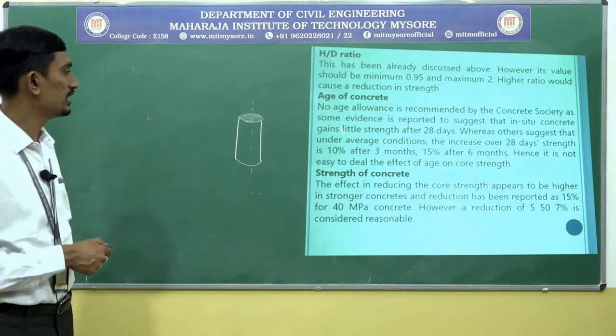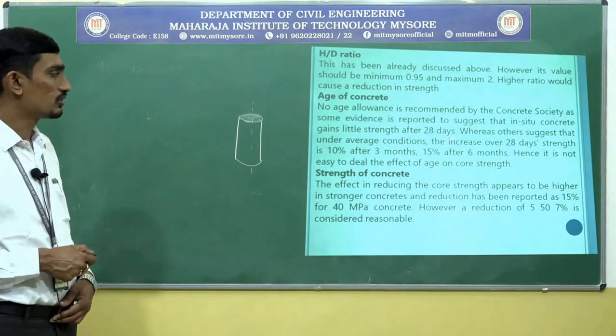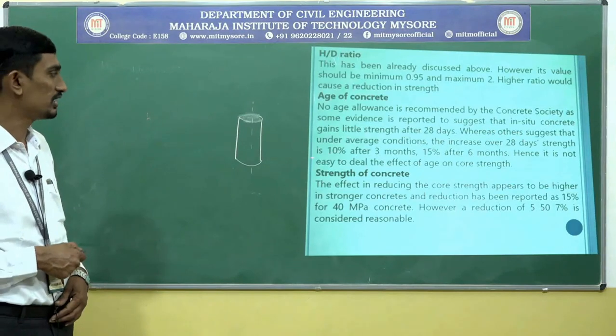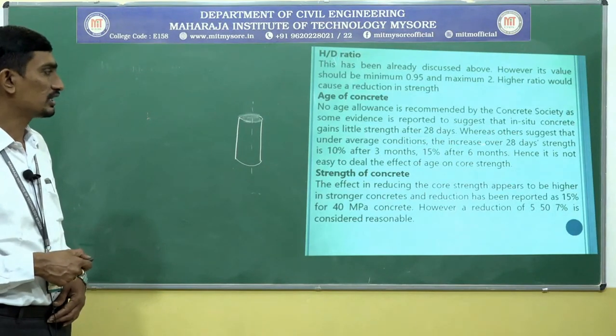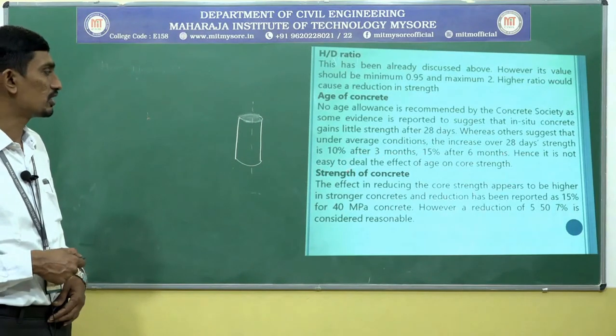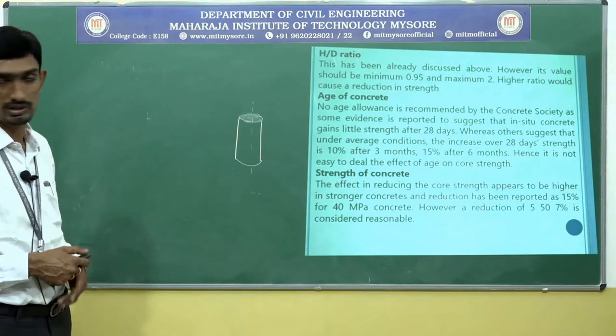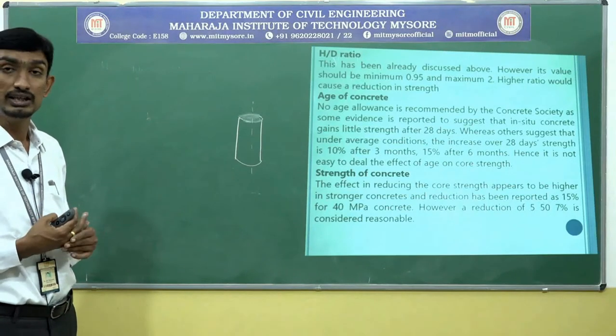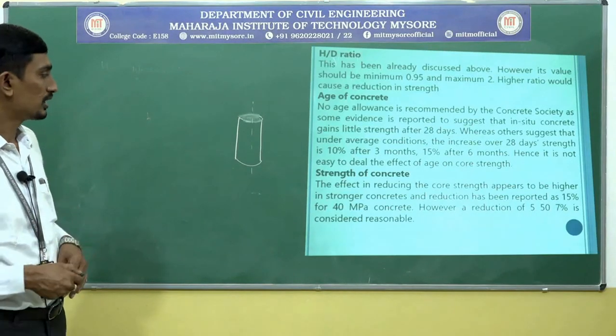Next, age of the concrete. Age of the concrete also plays a role. You can see here, on average, the increase over the 28-day strength is 10% after 3 months and 15% after 6 months. Hence, it is not easy to deal with the effect of age on the core strength. So it varies depending upon the age of the concrete. Next, strength.